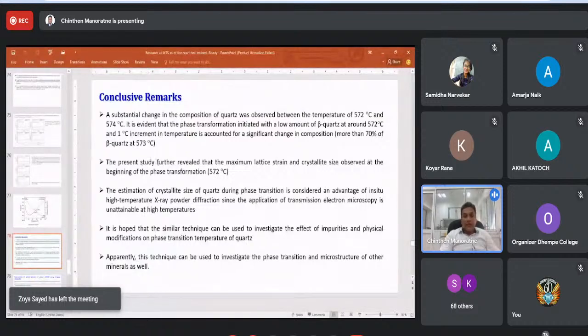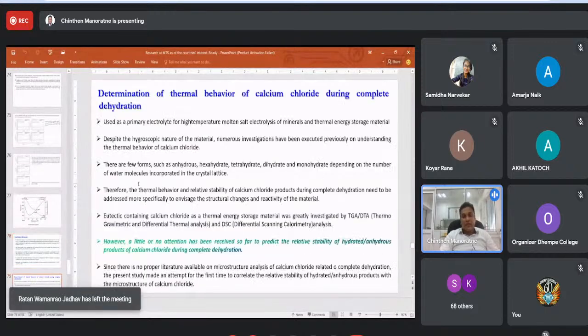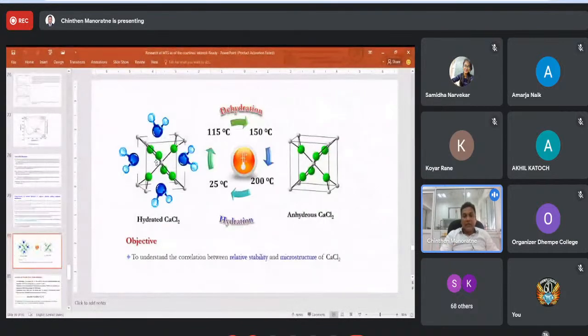The present study further revealed that the maximum lattice strain and crystallite size were observed at the beginning of the phase transformation. Like that, we have analyzed this microstructure. I won't go into detail on this. Here we also used calcium chloride as an electrolyte in our reactor, and we also studied the hydration and dehydration properties at elevated temperature. I will just briefly go through.